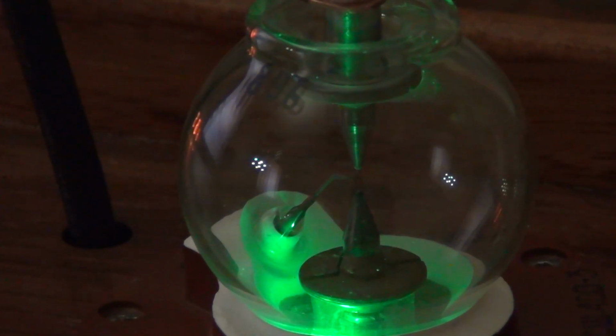After 1-2 weeks of using, I don't know exactly, but I think the situation was next. Sparkle, temperature and pressure inside the sparkle is high. It leads to producing some quantity of nitrogen oxides, and this reacted with this water which came inside the lamp, and that's why it produced some nitric acid. And this nitric acid influenced the electrodes and gave a corrosion of this electrode.